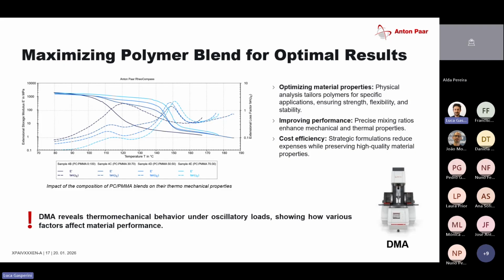But if I take a look at the loss factor here, I have two peaks. So I have the peak here from the PMMA, and I have a second peak from the PC. So why is this interesting? Because if you remember the shopping bag, the grocery bag example, the sample actually has two glass transition temperatures.